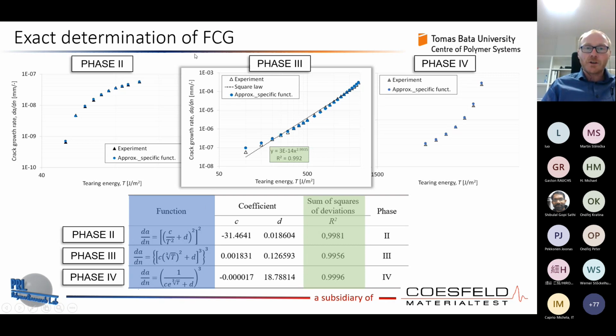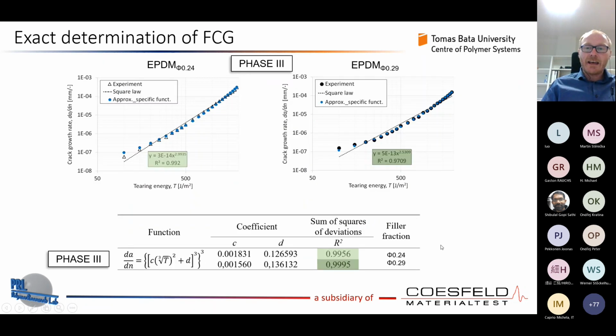We can see that for the third phase, stable crack growth, this line is the power law, and the power law has a sum of square of deviation of 0.992. With our defined specific function, we are at 0.9956. So let's say it's for sure better. However, even 0.992 is a great result. What we need to say is that for this material it's okay. We can be much more precise than a power law, and what we expect is that with other polymers like natural rubber there will maybe be a larger difference. Yeah, we need to investigate. However, using the specific functions makes sense for getting precise data.